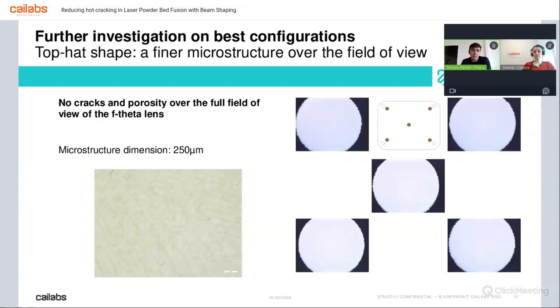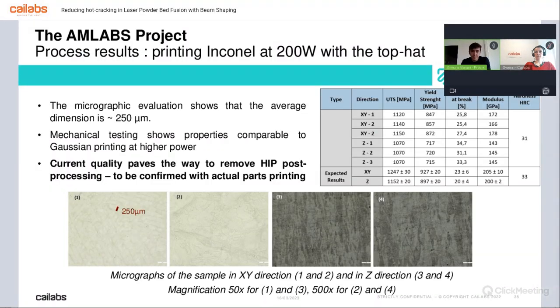of the top hat. For the top hat, we have chosen the highest scan speed that we have found with a high density, and so 920 millimeter per second. And we have seen again the repeatability of the application of a beam shaper on a laser powder bed fusion machine. Because again, we have no cracks and no porosity at all on all the specimens around the base plate. This time, the laser spot is half of the one of the ring shaper. And then we also have performed some